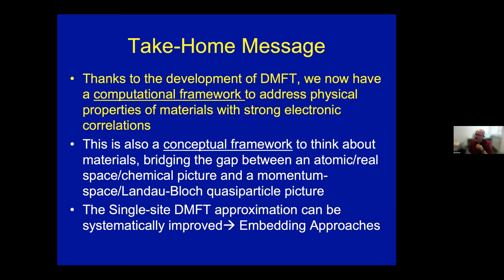What I believe is that in the higher temperature regime of systems that have a Mott critical endpoint, like the BEDTs or V2O3, this change of the nature of screening, because of course screening is not only from that narrow band. That's the key point, right? Screening is from all the other electrons, which already do a great job, even in the localized phase. For example, if you calculate the unscreened matrix element of the Coulomb interaction in atomic wave functions in the insulator, that would be 25 eV. If you calculate the screened Coulomb interaction, even in the insulator, it's going to be 3 eV, right? So all the electrons participate. This is why we need something like GW.